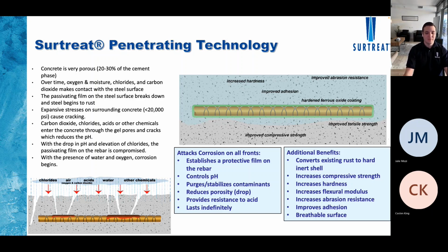So what we do is we migrate through the concrete, through those same gel pores. The first thing that our product is going to do, or one of our solutions is going to do, is regenerate that passivating film. Make that rust that's there, that's active, in the cathodic stage, make it non-reactive, make it inert. Then our technology is also going to migrate through the gel pores, and it's going to start binding with the free calcium. That's going to displace any contaminants and any acids, any waters, any chlorides that are there. It's also going to turn those chlorides into an inert state so that they're not water soluble anymore. So once you do that, you basically prevent that process of the pH dropping. You prevent that from happening again.